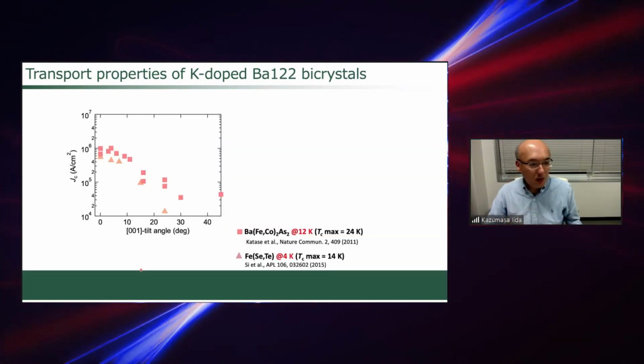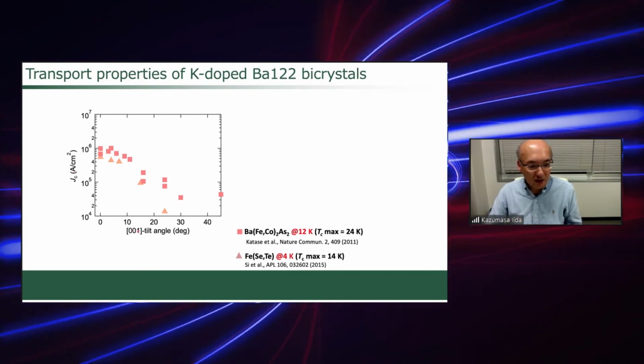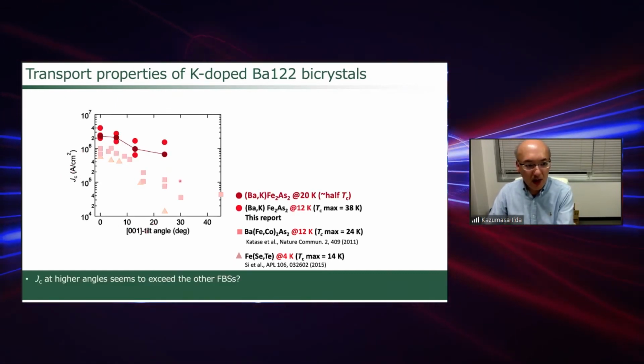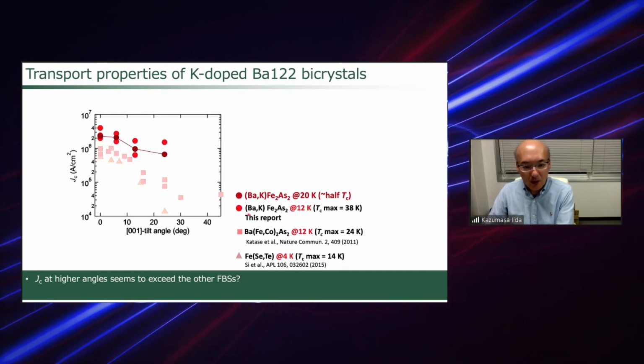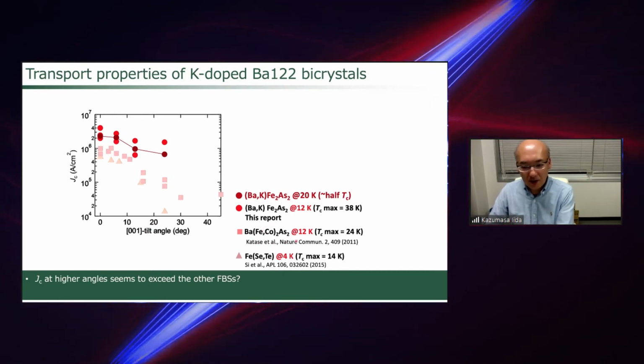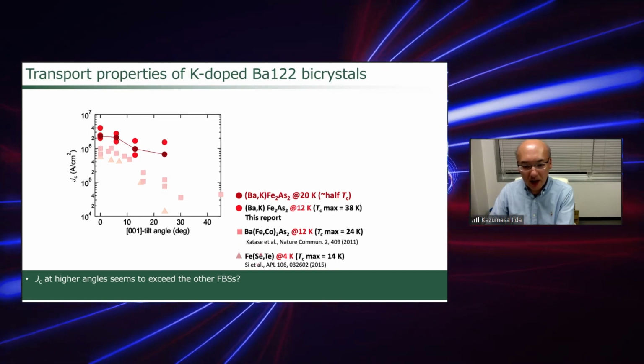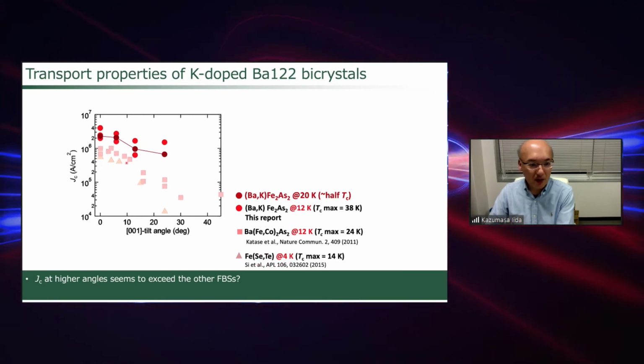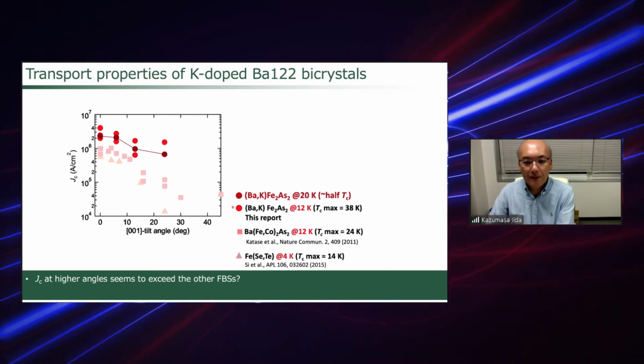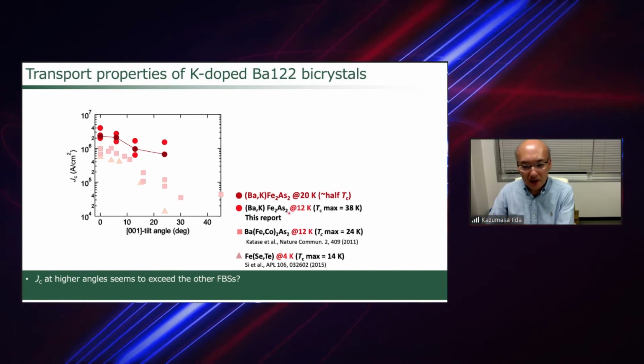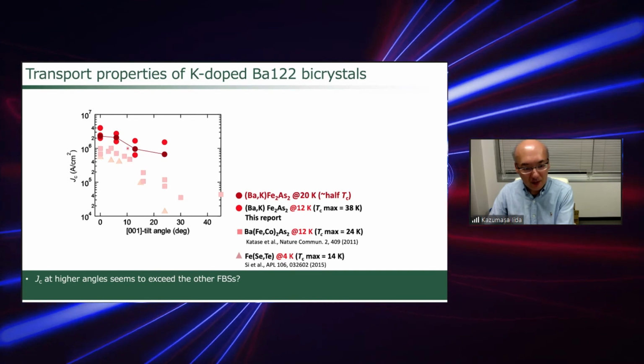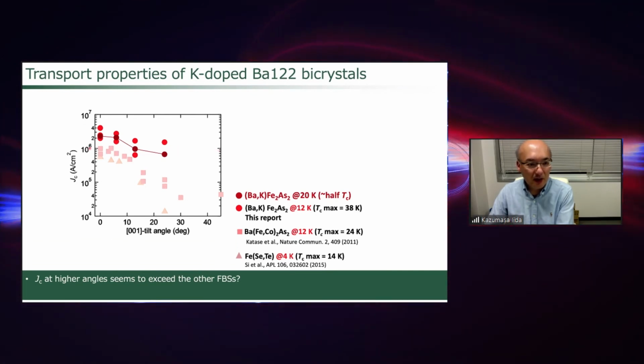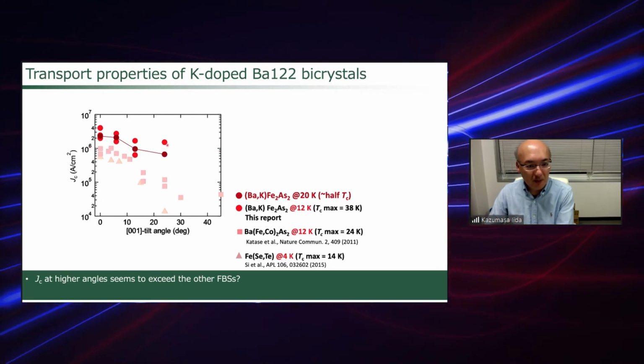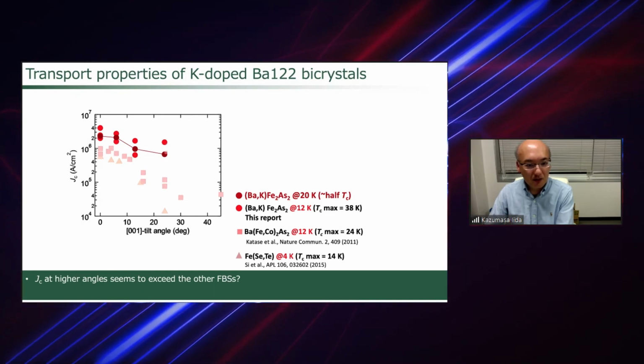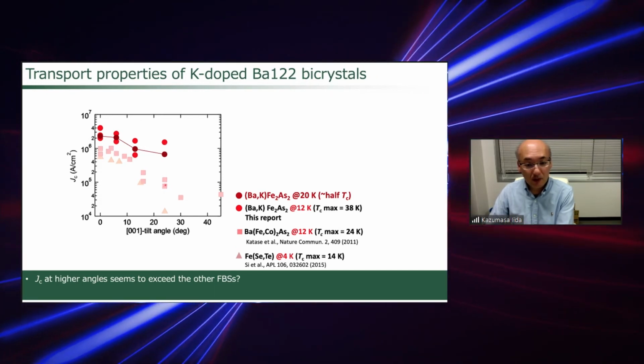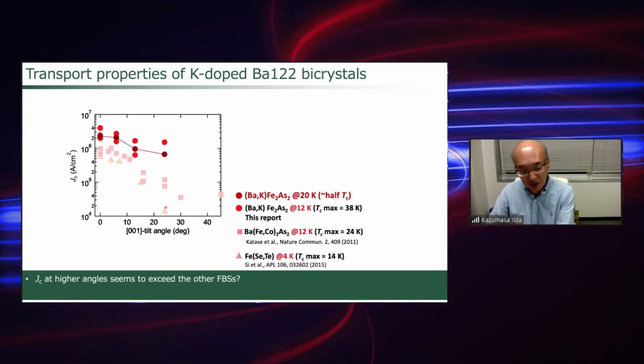So now we plot the intergrain Jc as a function of the misorientation angle for comparison with cobalt-doped barium 122 measured at 12 Kelvin, and iron selenide telluride measured at 4 Kelvin, which are also plotted in the same figure. And here is our data at 12 Kelvin. As I mentioned before, the intergrain Jc exceeds 1 mega ampere per square centimeter, which is quite high compared to the cobalt-doped barium 122 and the iron selenide telluride.